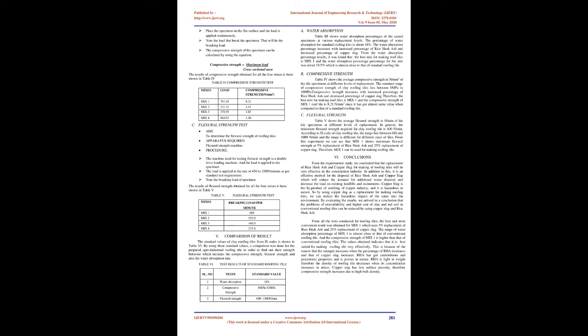Flexural strength test. Aim: to determine the flexural strength of roofing tiles. Apparatus required: flexural strength machine. Procedure. The machine used for testing flexural strength is a double lever loading machine, and the load is applied to the specimen. The load is applied at the rate of 450 to 550 N/minute as per standard test requirement. Note the breaking load of the specimen. The results of flexural strength obtained for all the 4 mixes have been shown in Table V. Table V. Flexural strength test.